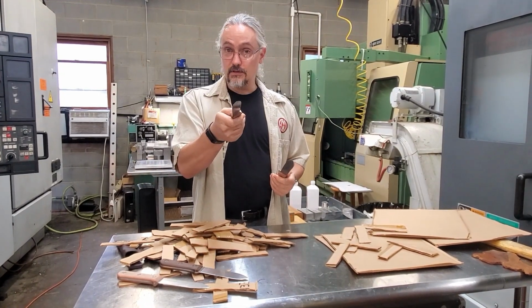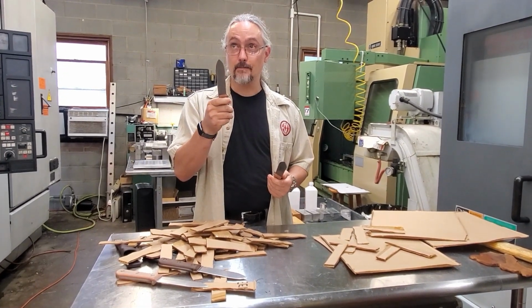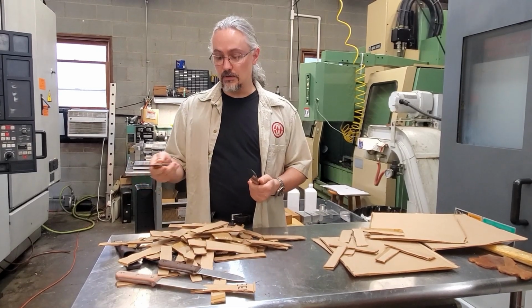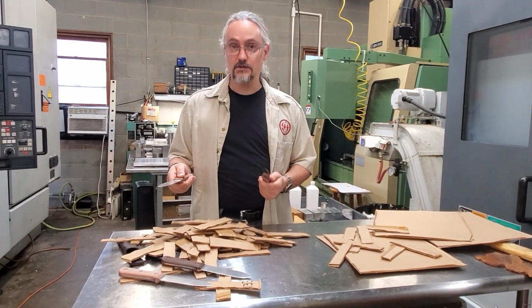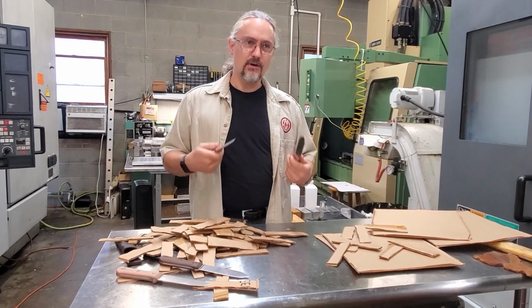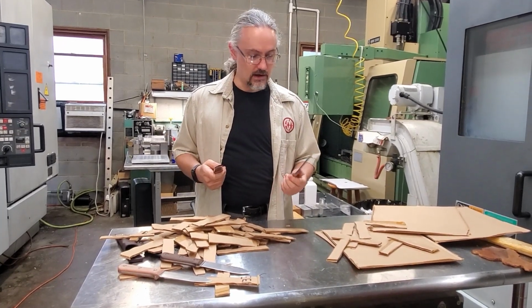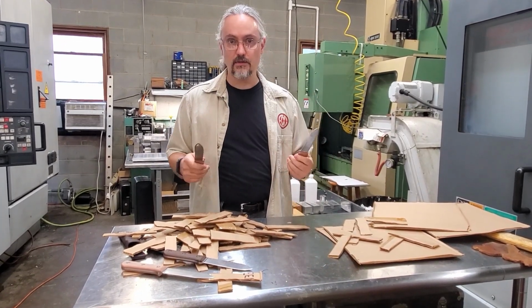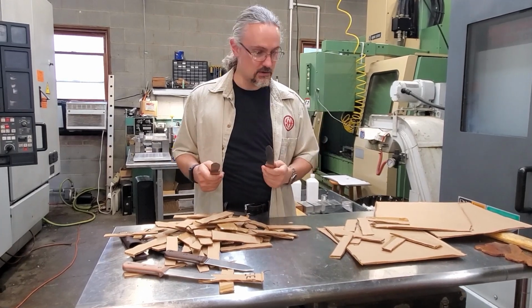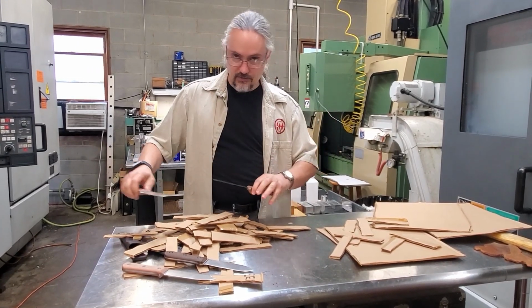It's the edge stability that causes issues that will cause poor edge retention in hard use, or what I would consider normal use. And it's an optimized heat treat, such as one of the better low temp tweaks and our Delta heat treat, that, you know, here it's all the same difference.